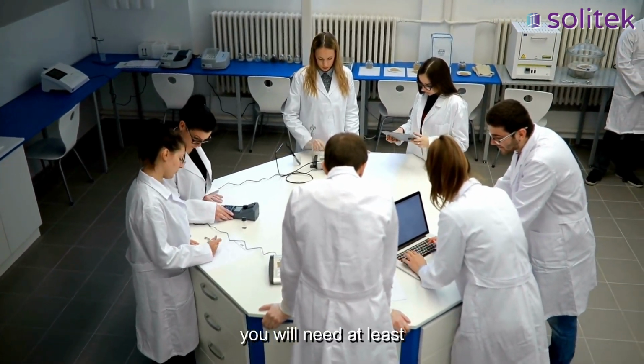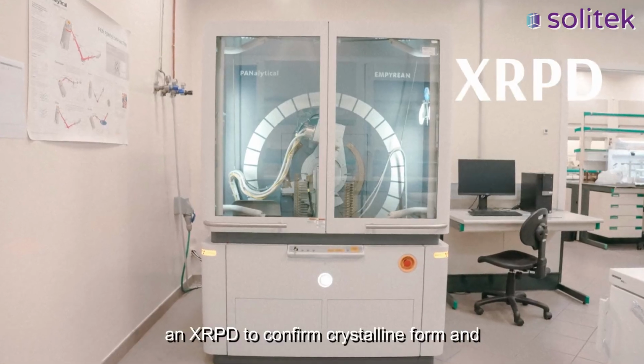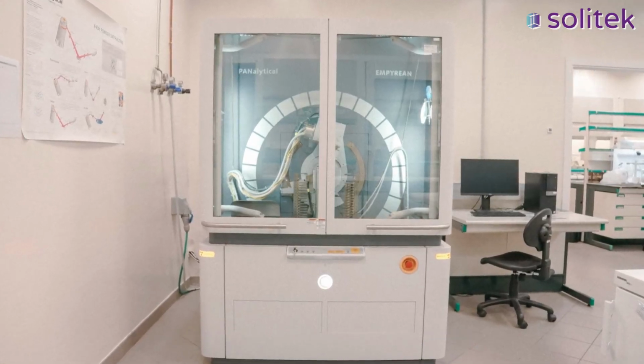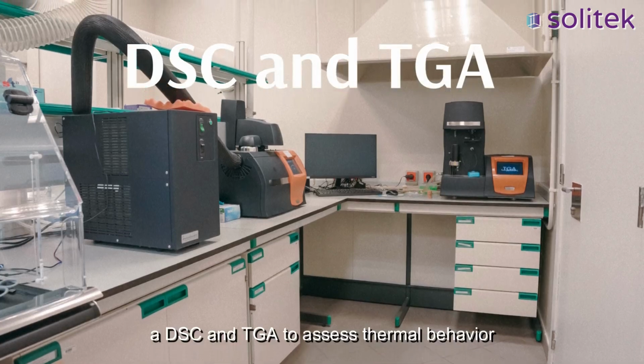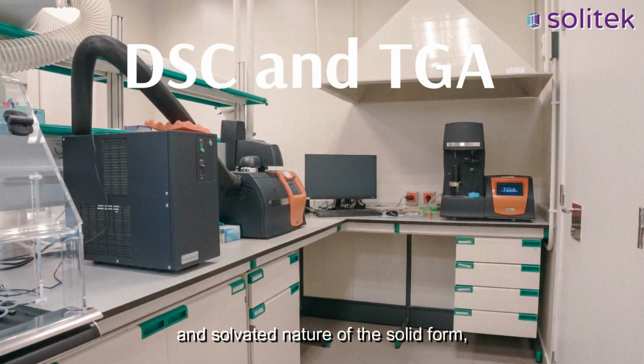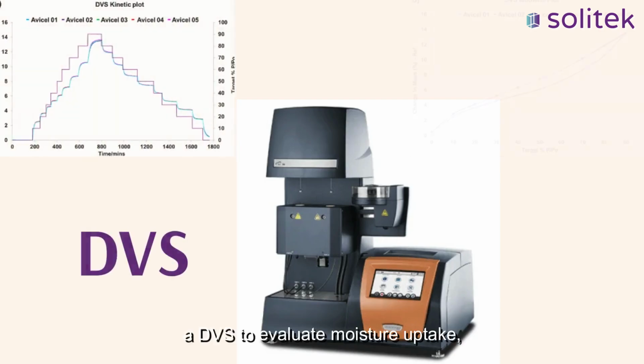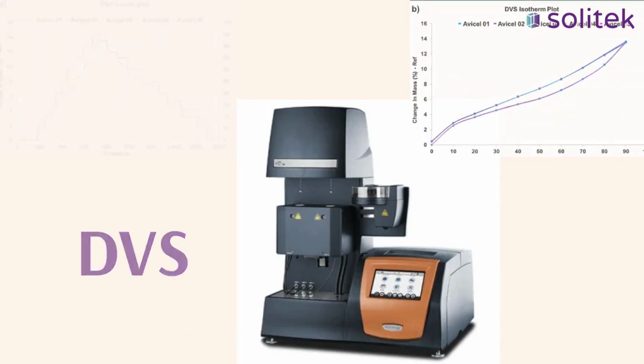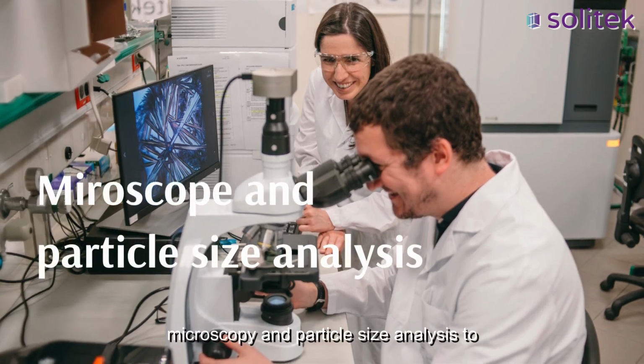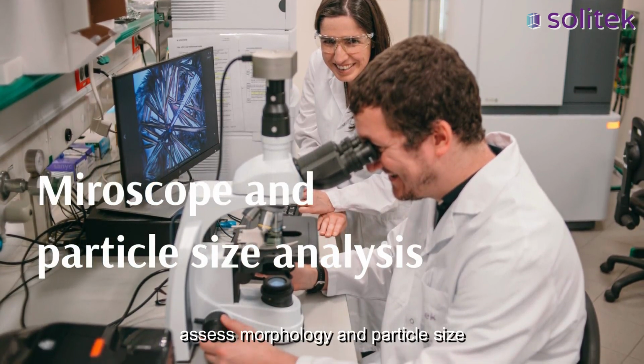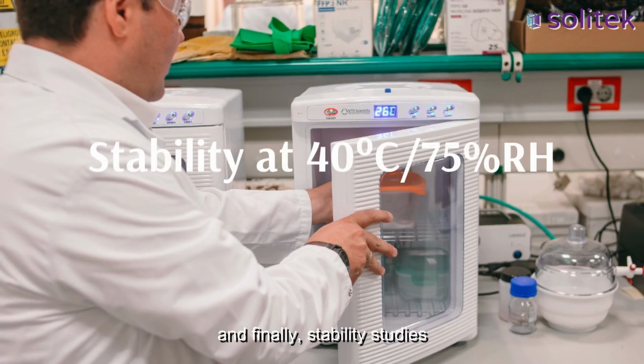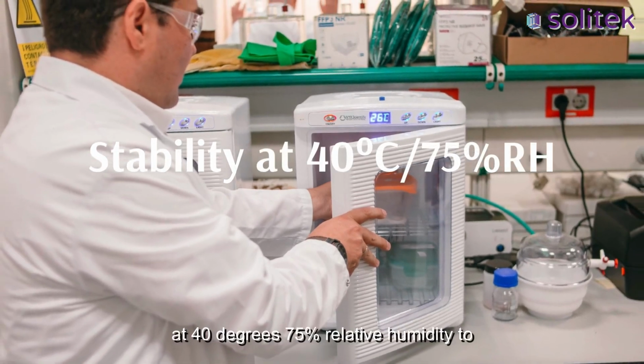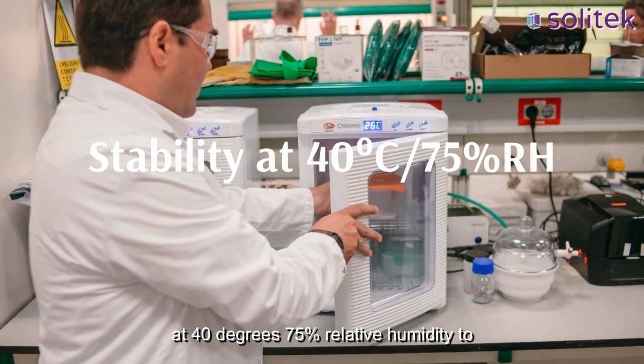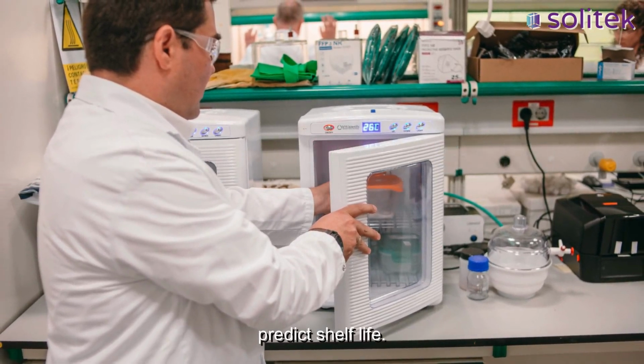will need at least an XRPD to confirm crystalline form and phase purity, a DSC and TGA to assess thermal behavior and solvating nature of the solid form, a DVS to evaluate moisture uptake, microscopy and particle size analysis to assess morphology and particle size, and finally, stability studies at 40 degrees, 75% relative humidity to predict shelf life.